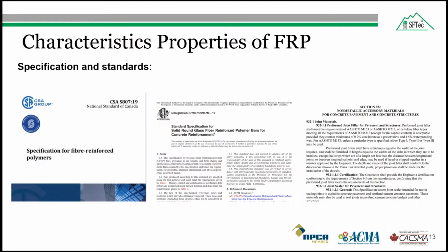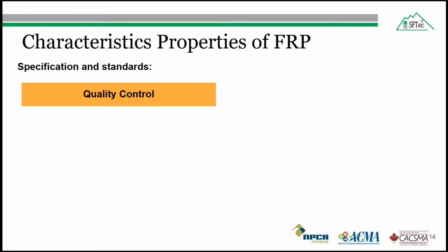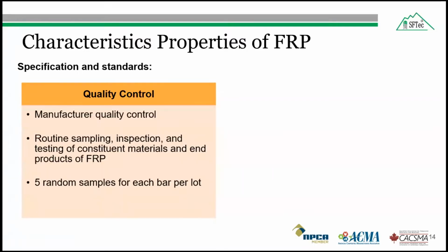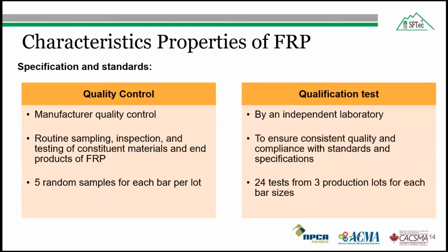There are two different types of test methods which are used. One for quality control and another for qualification. I will differentiate these two in the next slide. For quality control, the manufacturer should have in place a standardized quality control program that includes routine sampling, inspection, and testing of constituent materials and end products of fiber reinforced polymers. Documentation of test results and management of materials is very important for the manufacturer. Both CSA S807 and ASTM D7957 recommend testing of 5 random samples from each production lot, and the qualification tests are done by an independent laboratory for short and long-term performance of the fiber reinforced polymer products.